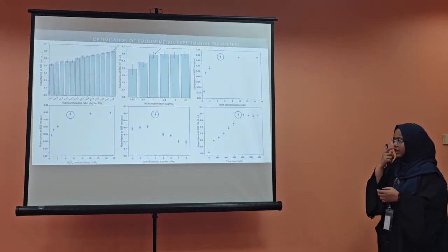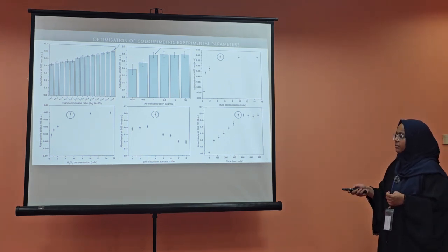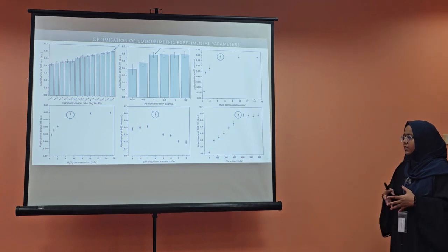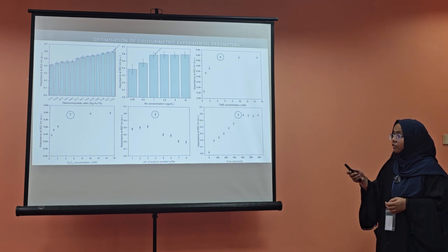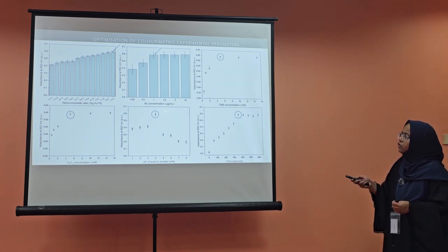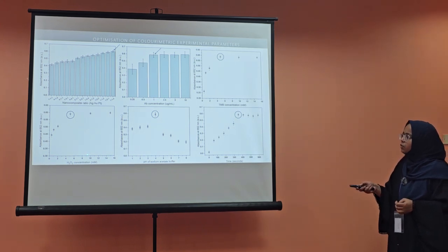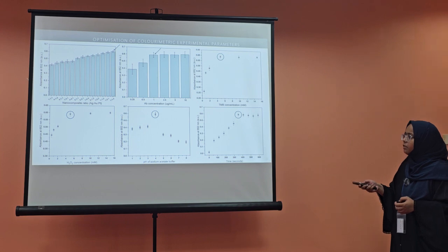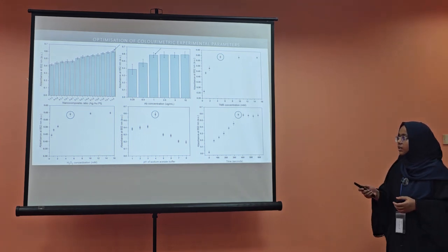Several parameters were optimized, including the nanocomposite ratio, antibody concentration, TMB, H2O2, pH of sodium acetate buffer, and time. The nanocomposite ratio of silver, gold, and platinum was optimized to 1:1:4, where maximum absorbance was observed. Antibody concentration was optimized to 1 microgram per ml. TMB and H2O2 concentration was optimized to 5 millimolar. pH was optimized to 4, and time was optimized to 360 seconds, that is 6 minutes.